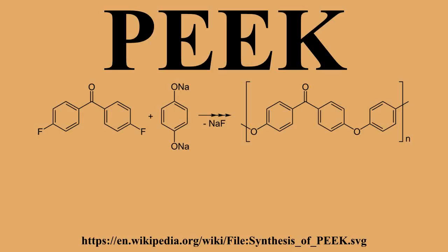Typical is the reaction of 4,4-difluorobenzophenone with the disodium salt of hydroquinone, which is generated in situ by deprotonation with sodium carbonate. The reaction is conducted around 300 degrees Celsius in polar aprotic solvents, such as diphenylsulfone.